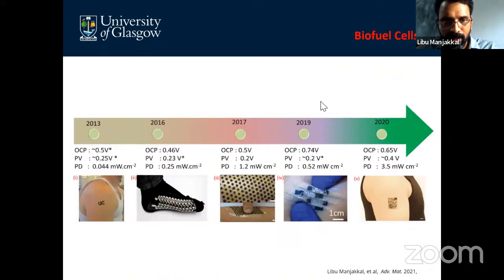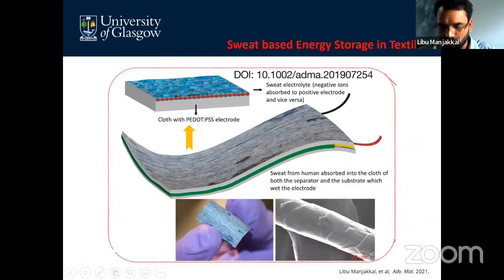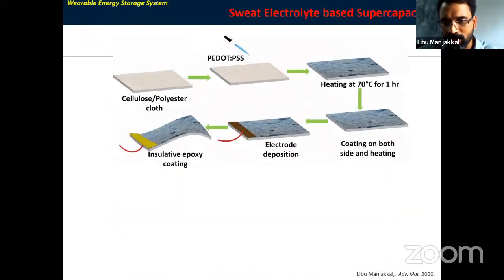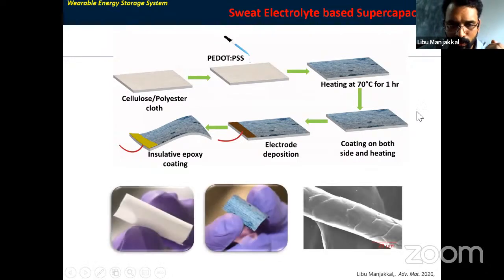Prior to that, you can see here the various biofuel cells and the growth in biofuel cells. If you would like to see more, we recently published a review article in this area in Advanced Materials. So when coming to the sweat-based work, I need a substrate which can absorb human sweat very easily. One of the most important, I found, is our dress, our cloth. So I used a cellulose polyester cloth and converted it into a conductive substrate by using PEDOT:PSS. And then I applied the electrode on both sides of the substrate, and it can act as a device.